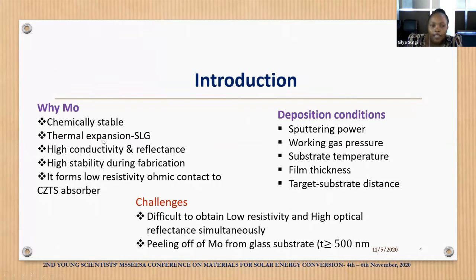The best parameters can be obtained with molybdenum back contact when the variation of different deposition parameters is taken. This includes sputtering power, working gas pressure, substrate temperature, film thickness, and target to substrate distance. And today we are going to focus more on 3 parameters, which are sputtering power, working gas pressure, and film thickness. Also, there are a lot of challenges regarding molybdenum back contact. The first challenge facing the single deposition of molybdenum is that it is difficult to obtain low resistivity and high optical reflectance simultaneously. And the other challenge is peeling off of molybdenum from the glass substrate when thickness is greater than 500 nanometers.